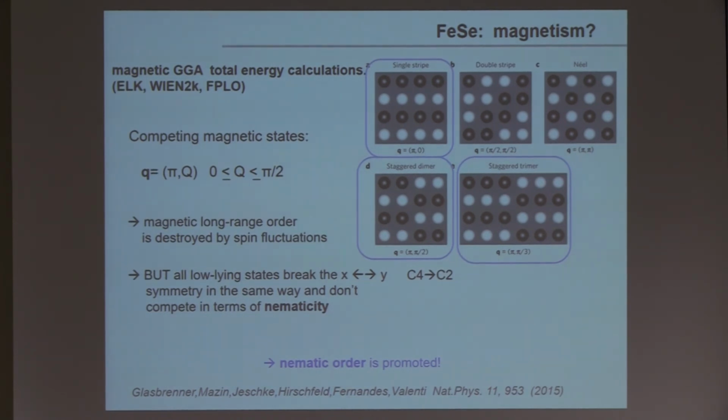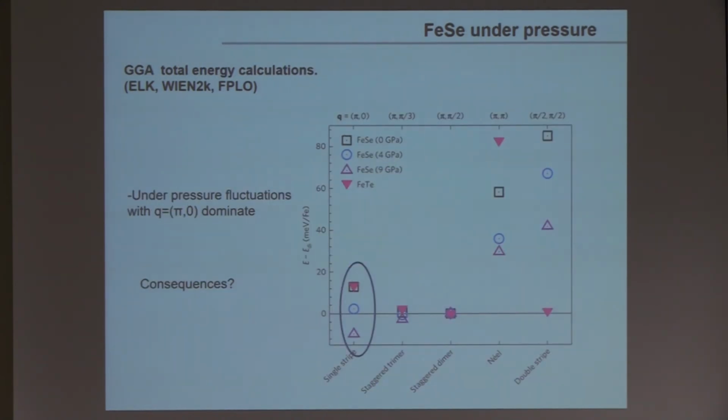And we could understand from that, in fact, that this magnetic frustration preserves nematic order because you break the C4 symmetry, but because of the frustration over which should be the Q that gives you the ground state, the system remains nematic. There is no way for the system to decide which is the state that is going to stabilize it.